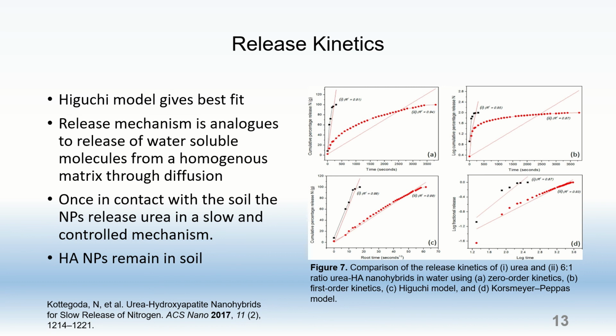Now, the release kinetics were studied using pre-existing models, and according to the R-squared value, the Higuchi model gave the best fitting line, shown here, and it follows a Fickian diffusion model. Since it follows this form of Fickian diffusion law, it can be assumed that the release mechanism is analogous to the release of water-soluble molecules from a homogeneous matrix through diffusion, which is commonly found in slow-releasing drug formulations. So once the nanohybrids come into contact with the soil, the urea releases from the hybrid in a slow and controlled manner through a diffusion control mechanism, and leaves the nanoparticle in the soil, and these nanoparticles are not absorbed by the plant.